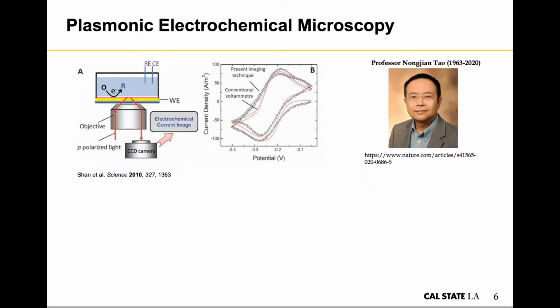So in 2010, he published the first paper utilizing SPR imaging setup to probe electrochemical reactions. He used several examples. One of them is to use the imaging technique to detect the TNT residue in a fingerprint. Here you can see that the red line represents the traditional electrochemical cyclic voltammetry, and the dotted line is extracted from SPR images, and they show a very good fitting, which is the first demonstration of using this surface technique. We can indirectly gain electrochemical reactions at local positions.